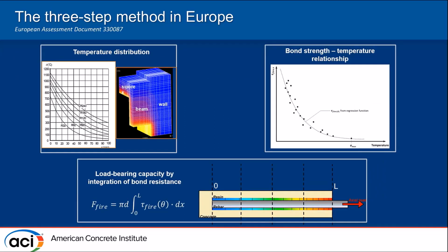So a method was established about 10 years ago and is today used in Europe for design and evaluation of post-install rebars. The method has three main steps that we see here. In the first step, we carry out a thermal calculation inside the structure in order to know at each time what is the thermal distribution along the rebar. And this can be done either by chart reading or by numerical simulation. In the second step, we establish a relationship between bond strength and temperature, and I'll come back to this later. This is a product-dependent relationship. It depends on the mortar that we're using.